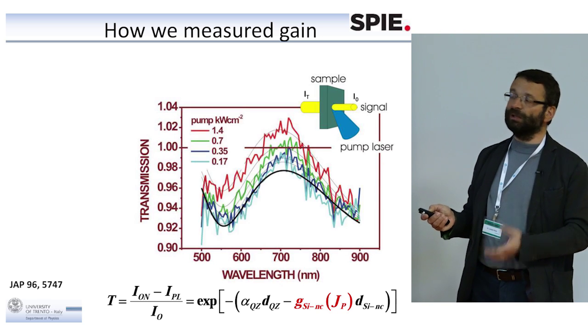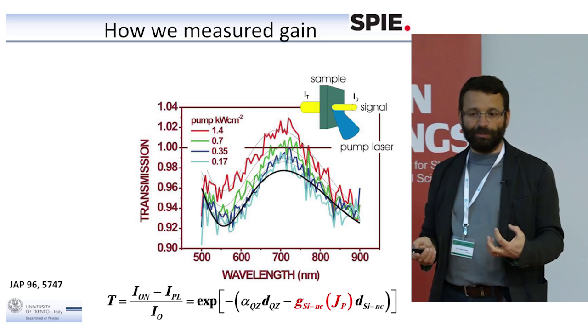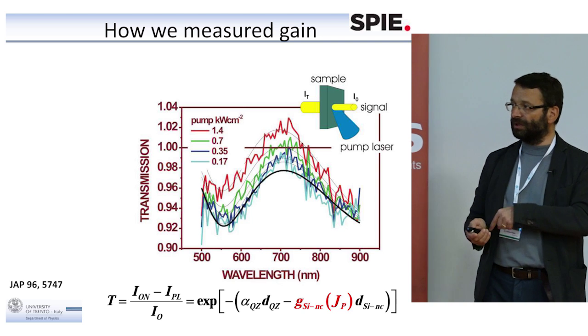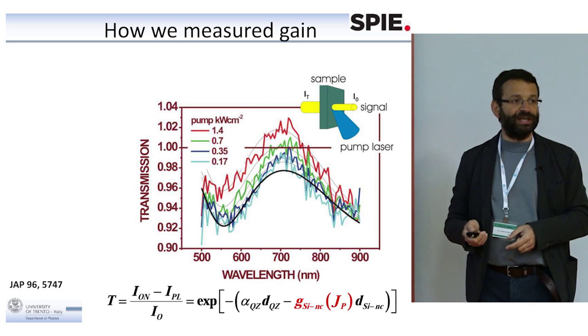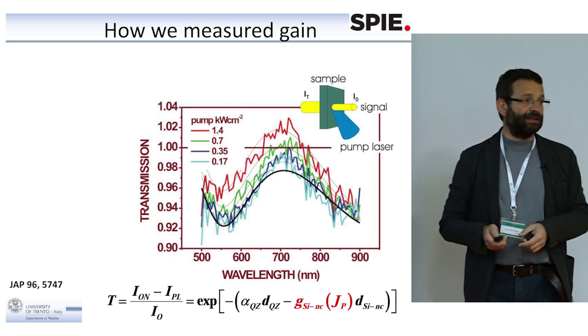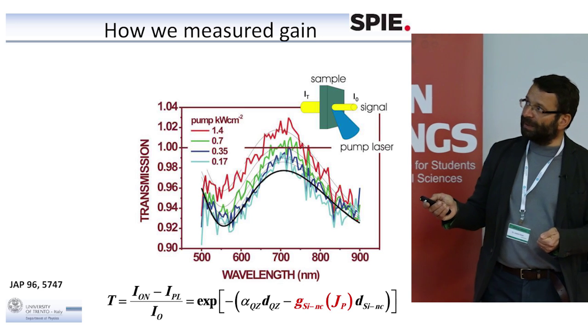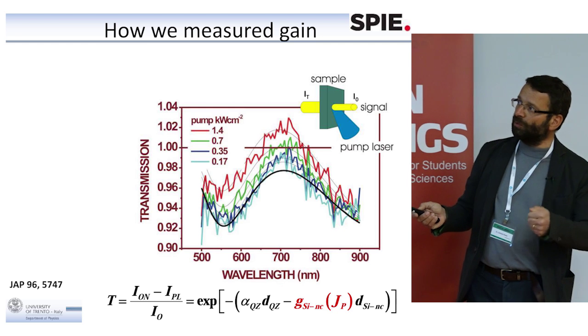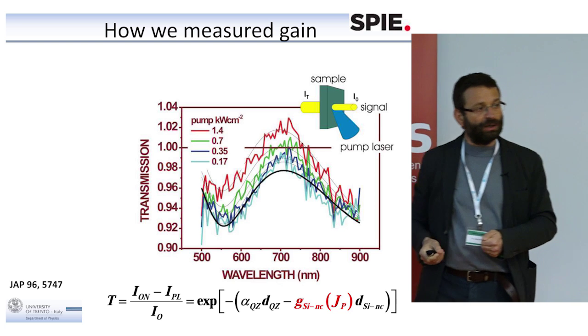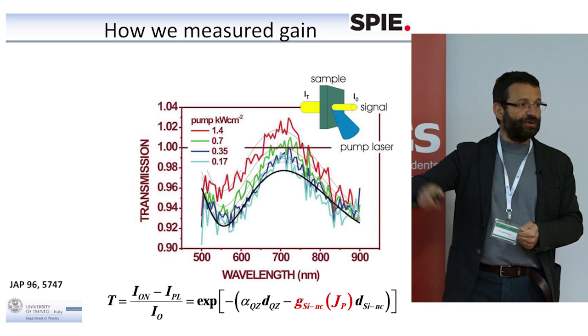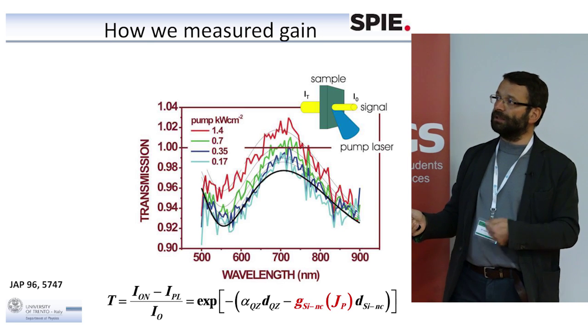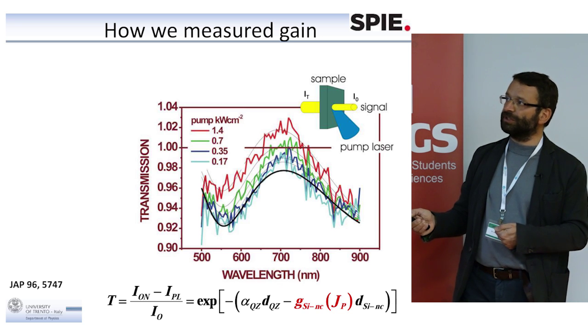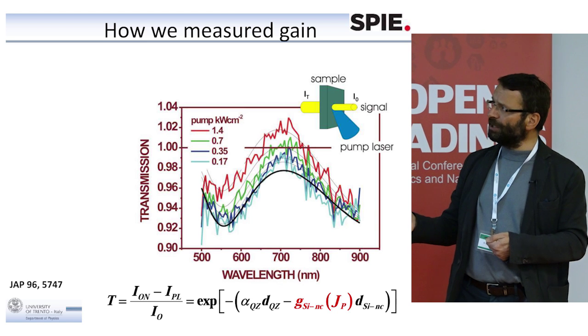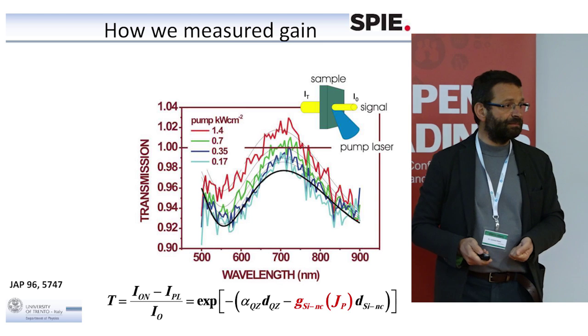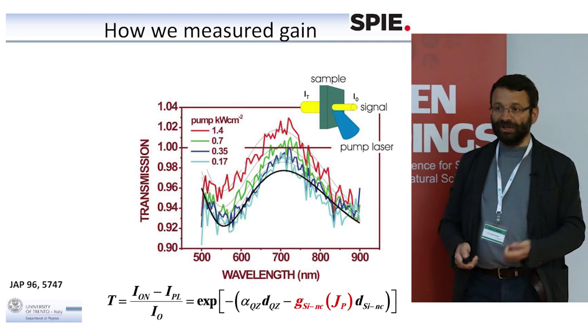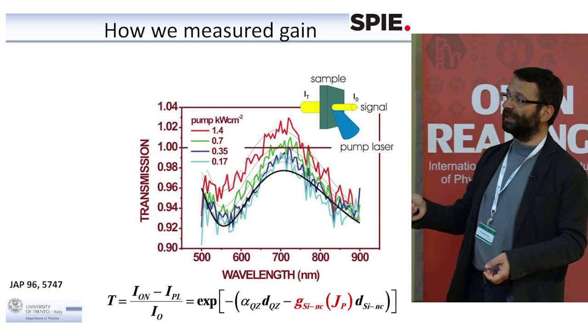However, now, if we use a blue laser, it is absorbed by the nanocrystal by promotion of one electron from the valence band to the conduction band. Now, if you pump with the blue laser, you observe that the transmission is affected by the power of the pump, and then by increasing the pump power, you excite more and more electrons up to a level where you get population inversion. So you have more electrons in the conduction band than in the valence band. You have population inversion, so you can get a gain from the nanocrystal. And indeed, if you look at the intensity of the transmission, you see that the transmission is larger than 1. So it means that the signal has been amplified by the nanocrystal. More light out than what you get in. The difference is coming from the blue laser, clearly, from the pump laser. So this is very important.